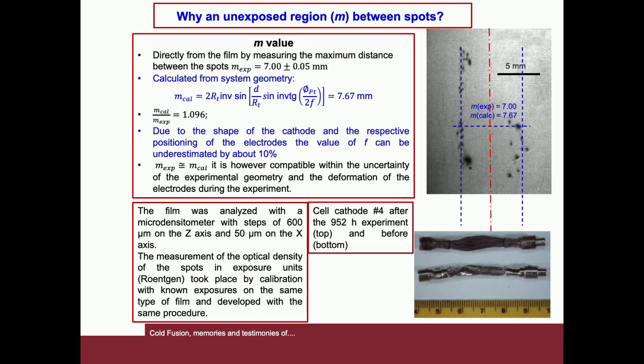Shown here is the cathode of cell 4 after 952 hours of experiment compared to the electrode before the experiment. The X-ray film was analyzed with a microdensitometer with steps of 600 microns on the z-axis and 50 microns on the x-axis. The measurement of the optical density of the spots in Röntgen exposure units took place by calibration with known exposures of the same type of film and developed with the same procedure.